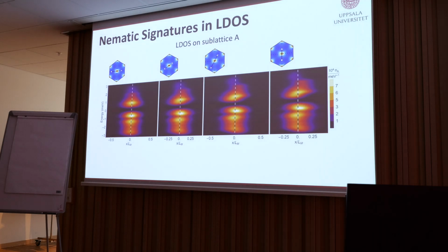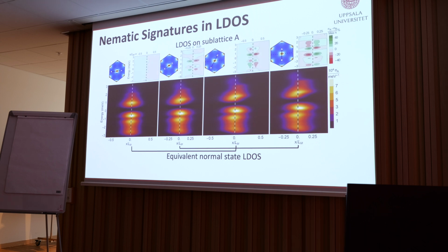You can actually pick up nematic signatures in the density of states, but you have to be a little careful. You have to do it sublattice resolved. So this is data on the sublattice A in each unit cell. So we plot the density of states here as a function of this angle, going along these arrows here. And in the normal state, number 1 and 3 and number 2 and 4 should be equivalent. But as you see here in the density of states plot, they are clearly not equivalent. So this is a signature of the nematicity broken in the superconducting phase. But if you were to plot things in sublattice B, you would get the opposite. So if you average the two sublattices, you do not measure the nematicity in real space. But you will be able to see it if you sublattice resolve the structure. So it's a nematic and sublattice dependent state signature at least.